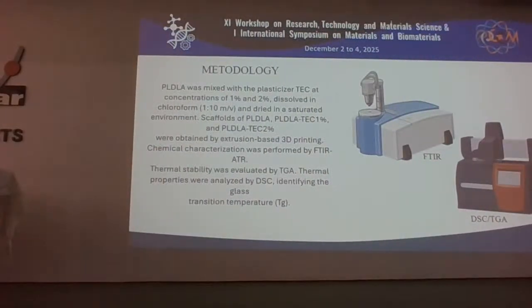Methodology: PLDLA was mixed with TEC at concentrations of 1% and 2%, dissolved in chloroform. Scaffolds of PLDLA, PLDLA TEC 1% and PLDLA TEC 2% were obtained by extrusion-based 3D printing. Chemical characterization was performed by FTIR. Thermal stability was evaluated by TGA. The thermal properties were analyzed by DSC.